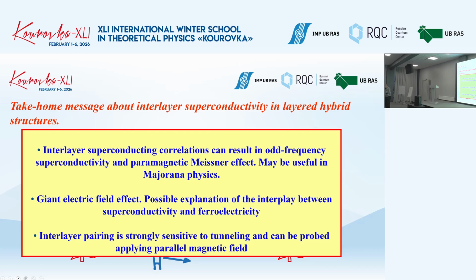But what I must say is that concerning this particular experiment, in fact, you do not have an isolated domain wall. You have many of them. When you do this polarization procedure, these superconducting wires overlap, and because of that it's not strictly one dimensional. This means that you badly need information about the domain structure. What's the size of domains? What's their shape? That's correct. To verify this scenario and to compare it with experiment quantitatively, you need information about those. That's correct. Sure. Okay, thanks.